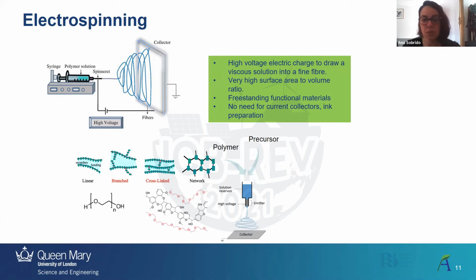Then you can add, if you want, some additional polymers. If the precursor you're adding is a ceramic one, you might need a polymer to help form the fiber shape, which can then be removed after thermal treatment anyway. And then you need a solvent to have your solution, and then you can add a lot of different components. For example, if you want to tune the porosity, you can add surfactants, or you can add a post-treatment of KOH, and you can also add nanoparticles of different electrocatalysts that will then be embedded in the fiber as you're spinning it. So that's a lot of options that this technique allows.